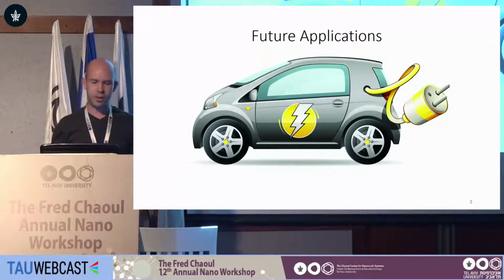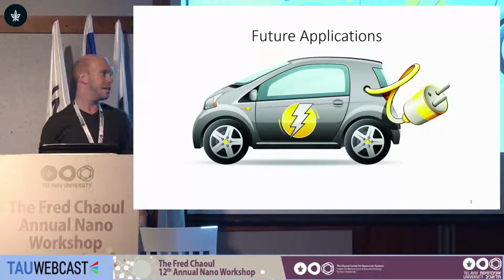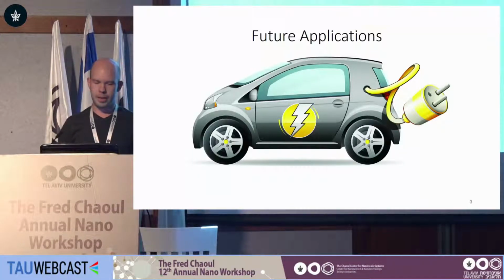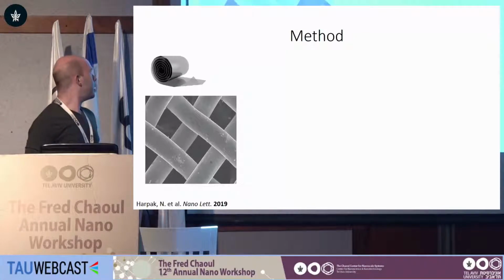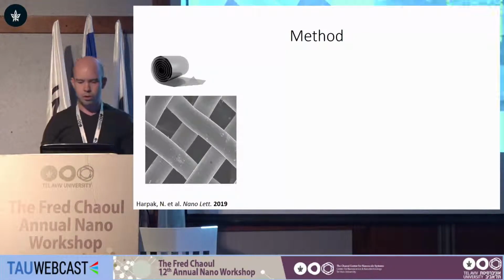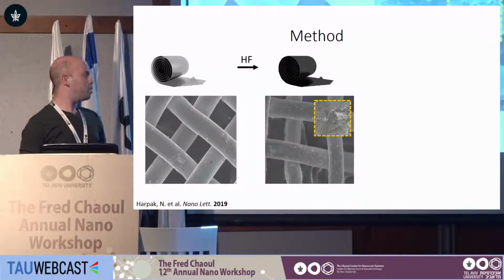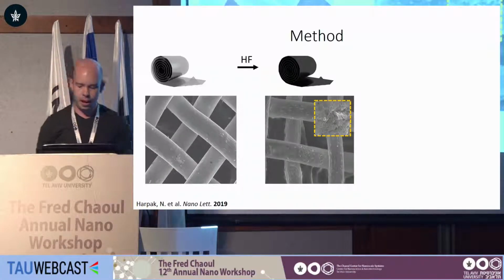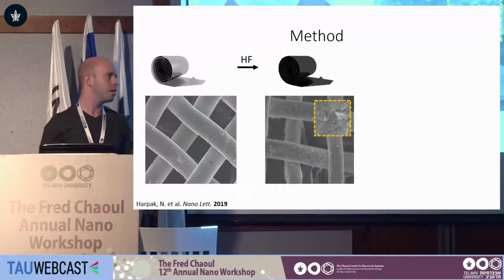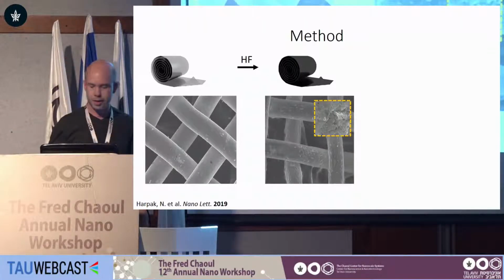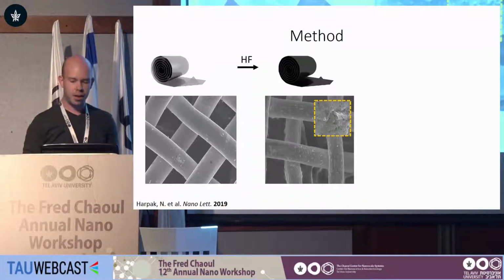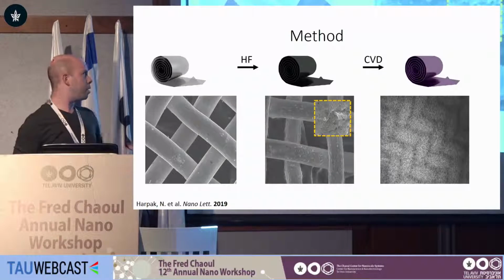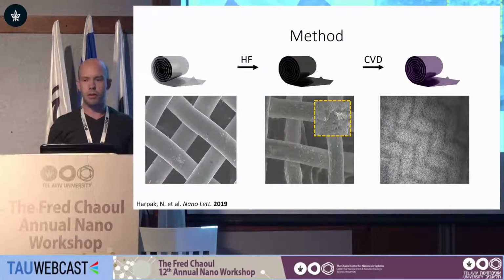Silicon has been chosen by many around the world to be the next generation anode material, but it hasn't been commercialized yet since it has a lot of problems. So I will tell you a bit about what we did. We took an ordinary stainless steel and we treated it with hydrofluoric acid. The hydrofluoric acid is selectively etching the iron and alters the chemical species of the surface, which creates a catalytic island that further in the CVD can grow silicon nanostructures at very low temperatures.